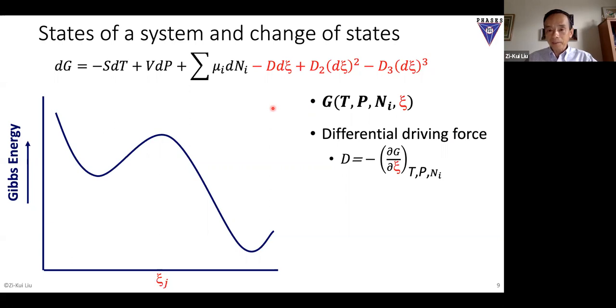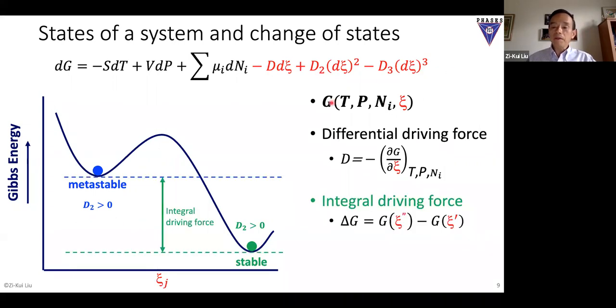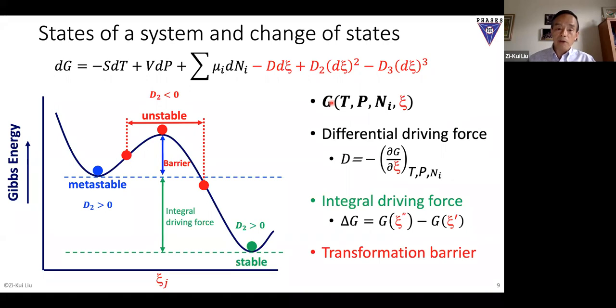You can calculate. However, I have a barrier. Right? So then you have to calculate the integral driving force. You have the metastable state of water. You have a stable state of ice. But both of them are stable because the second derivative is positive. So you have driving force. That's called the integral driving force from the beginning to the end. And between the two states, you have a barrier. So in the barrier, you have the unstable range. The second derivative becomes 0.